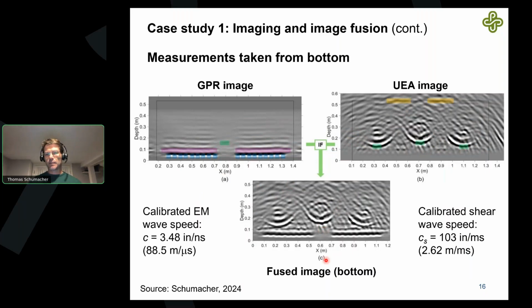Again, we use a little bit more complicated method, but this is what the fused image looks like. And you can see we have a very clear indication of the pre-stressing strands, but also the voids are shown very clearly. Further confirmation that's nice is if these reflectors actually line up, they're in the same position, then we also know that for both cases we assumed the right wave velocities. You can see here the wave velocity for the radar wave and the wave velocity for the shear wave. This is the ultrasonic array we use as a shear wave device. So about 2.62 meters per millisecond. That's a fairly strong stiff concrete, which tells us it's a dense concrete, which is likely a strong concrete.